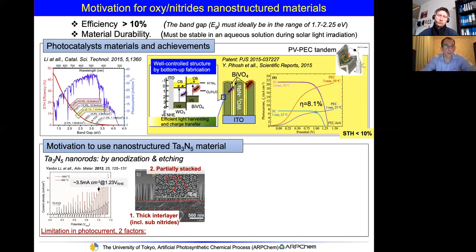From our previous work, where we worked a little bit on this material, we developed the nanorod. However, this nanorod was prepared by electrochemical processes, and there are two limiting factors. At first, during that process, a thick interlayer appears, and this subnitride layer is not well conductive. That means we have losses in the electron transport. And secondly, the nanorods are partially stacked. This is also bad because we have losses in the total surface area.